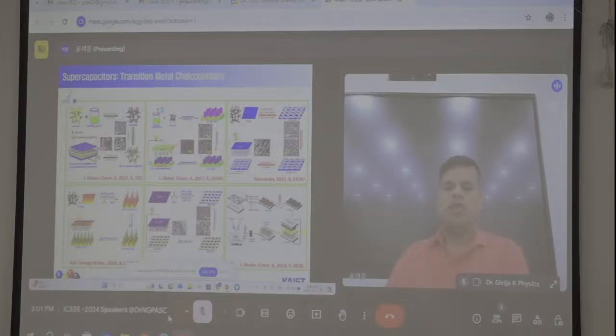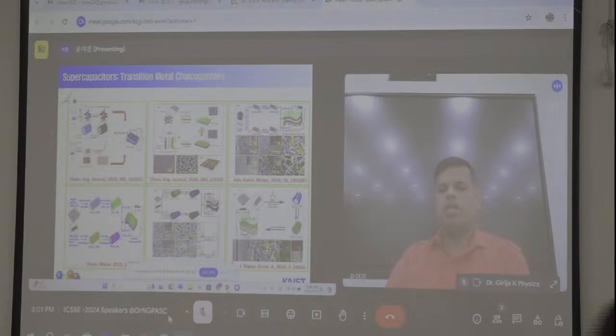Then when we go for the commercial aspect like flexibility, nickel foam also has some issues, because nickel foam cannot be bent many times, it will break. Therefore, we moved from the nickel foam to the carbon cloth. You can see the carbon cloth, and we directly grow the material over the carbon cloth. That material may be used for highly flexible energy storage devices, both positive and negative electrodes. And finally, we get high energy density and power density from our flexible energy storage devices.